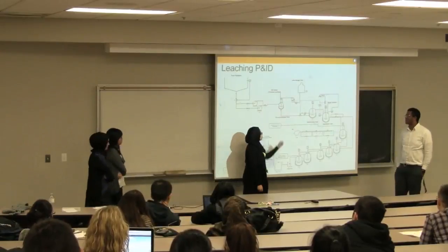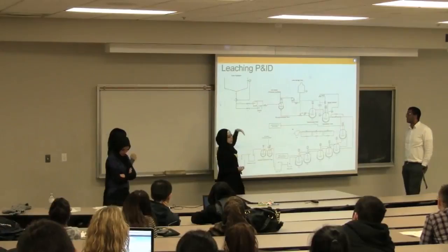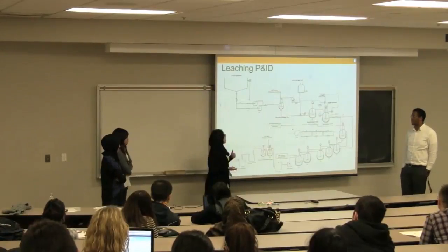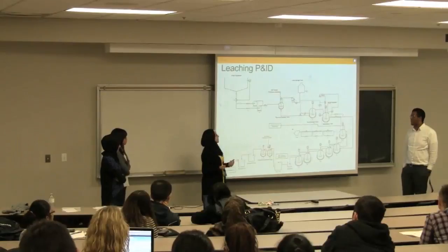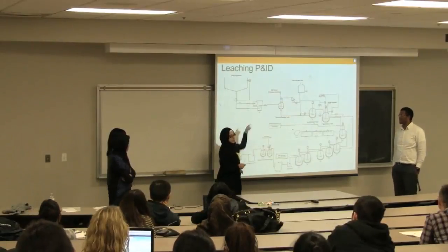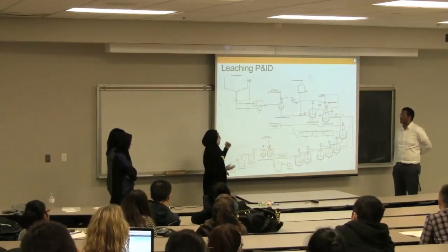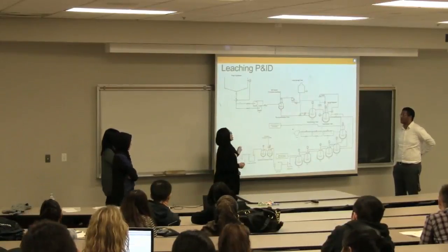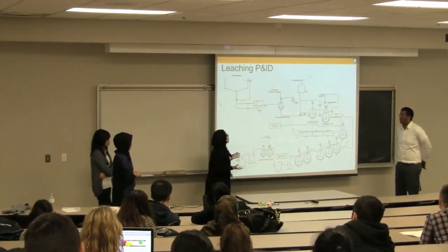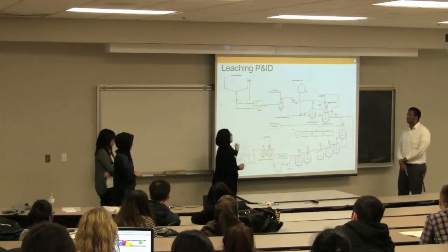That is due to the pre-neutralization tank, where, since the slurry is acidic due to the upstream processing, lime gets added to neutralize it and bring it up to the pH operating level we need for the leaching, which is between 11 and 12. Water is added in order to bring the viscosity and density of the slurry to the operating level required for leaching. We decided to over-design this tank because we want to accommodate more viscous slurry if needed.